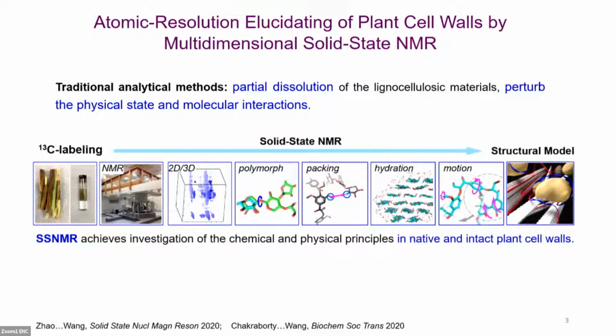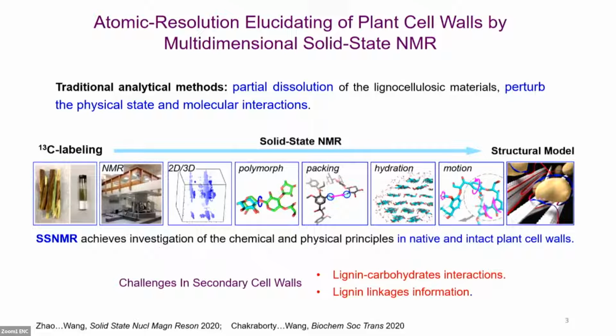We just need to pack the carbon-13 labeled plant stem into the rotor and collect a series of 2D and 3D experiments, and then we can get all the information that we want, just in native and intact cell walls. Our group has made several efforts on illustrating the primary cell wall information. Currently, the challenge is on the secondary cell wall. Could we detect the lignin to carbohydrate interactions, and could we get the lignin linkages information in the secondary cell wall?